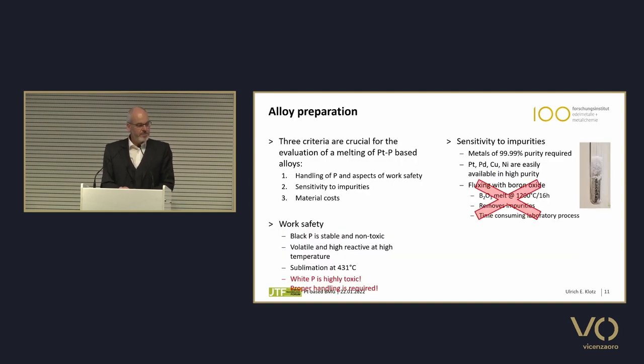So when we do alloy preparation, we have to work with phosphorus, so that's a bit tricky, because phosphorus is highly reactive, especially if it forms white phosphorus. White phosphorus is highly toxic, and it must be avoided that white phosphorus is forming. Therefore, you cannot simply put it into an open graphite crucible and melt it, because all the phosphorus will evaporate, will transform into white phosphorus, and so you have to be careful what you're doing. So don't repeat these experiments in your lab at home, and better ask for some assistance by someone who worked with these alloys already.